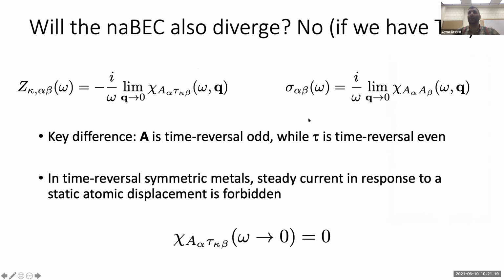Okay, so the optical conductivity diverges at low frequency. What about the Born effective charge? The difference between the Born effective charge and the optical conductivity is that instead of having a current perturbation and a current response, we have an atomic displacement perturbation and a current response. If we consider a crystal with time reversal symmetry, the current response is time reversal odd, while the atomic displacement response is time reversal even. Whereas in the optical conductivity case, we have two time reversal odd quantities. And so at zero frequency, we get a finite value, the Drude weight. For the Born effective charge, at zero frequency, the susceptibility vanishes.